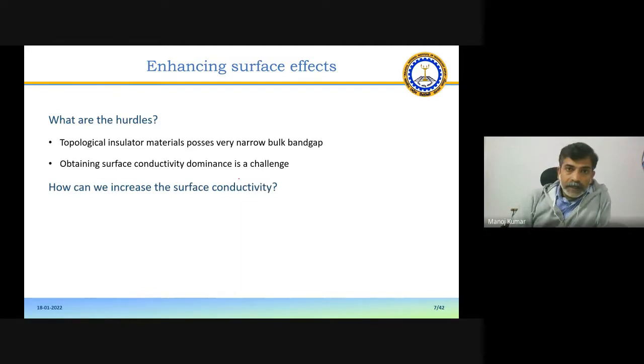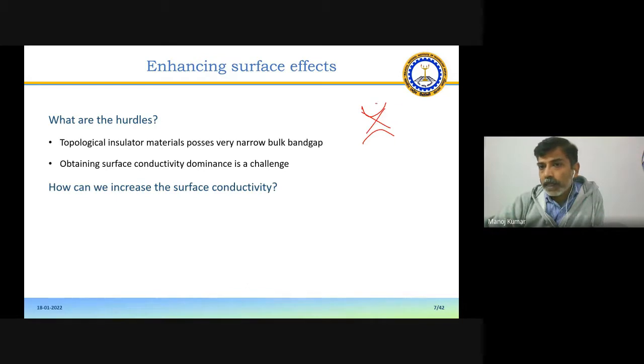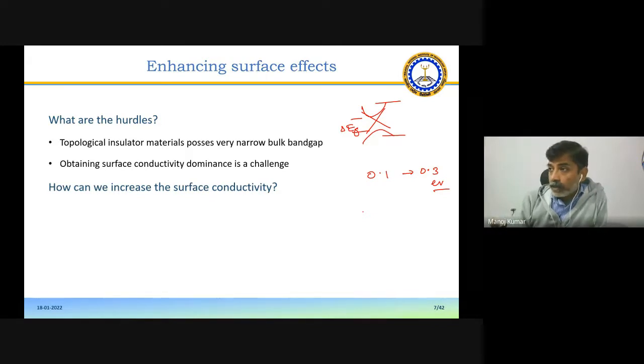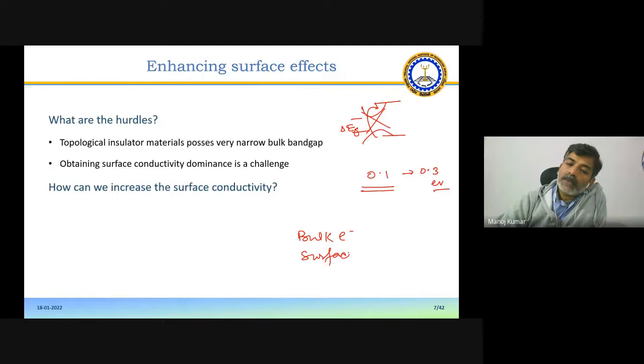So the main problem with this type of material is that there are two types of conduction. Bulk conduction is also a kind of semiconducting behavior with a gap. And this gap is very small, something like 0.1 to 0.3 electron volt, much, much smaller than silicon or germanium. So it's basically a narrow band gap semiconductor inside the bulk. And if the band gap is very small, sufficient energy can be given to the electron to overcome this gap, and then we see conduction through bulk electrons and conduction through these lossless surface electrons.